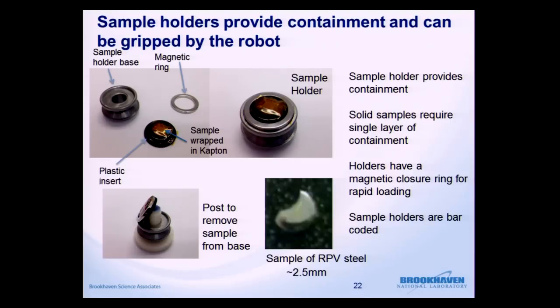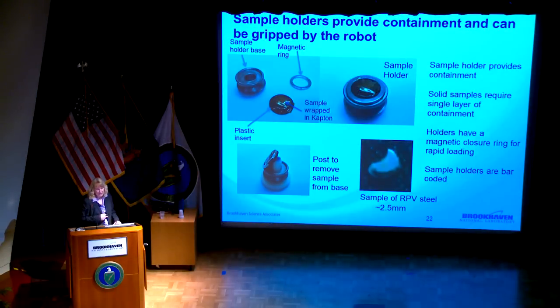We put it on the base and put the ring on; it has a magnetic closure to reduce loading time. And then when we want to remove the sample, there's a post that lifts the sample and lifts the magnet off. So the sample holder provides containment, and all the samples at the light source require at least a single level of containment. So none of the samples are loaded or unloaded at the light source.